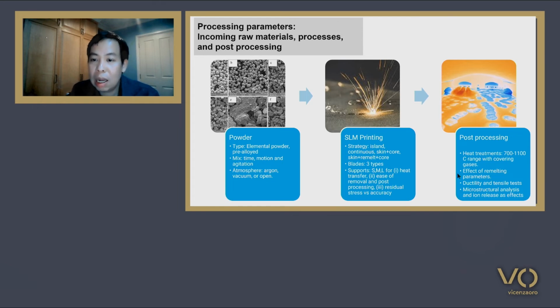For post-processing, we do heat treatments in the range of 700 to 1100 degrees Celsius with a covering gas like an argon atmosphere. We also look at the effect of remelting parameters in the laser itself during the 3D printing. And this could accomplish several mechanical properties of the materials, for example, ductile titanium. And we could also show this result by tensile test. We do a lot of microstructural analysis, and this also serves as a way to understand which post-processing technique is best for our samples.